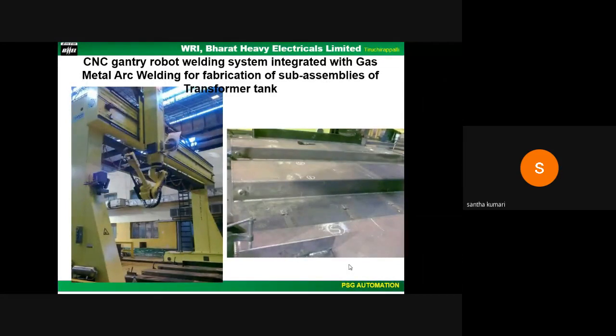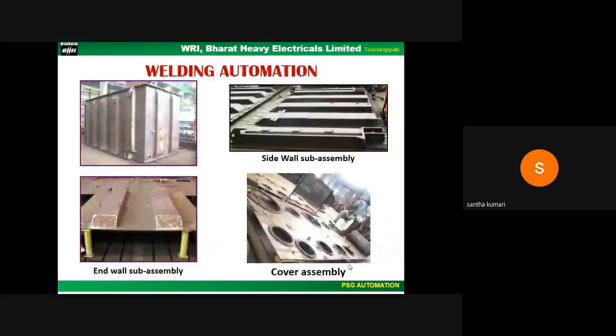Inverter-based power source MIG welding operating up to 400 amps with 100% duty cycle, with provision for welding in standard MIG, pulse MIG, and synergic MIG, was used here. With this system, transformer tank subassemblies are being welded, and because of this, the weld processing time of the components was reduced by 60%. The necessity for back chipping, dye penetrant test, and second side welding has been eliminated by developing parameters for full penetration joints from a single side.